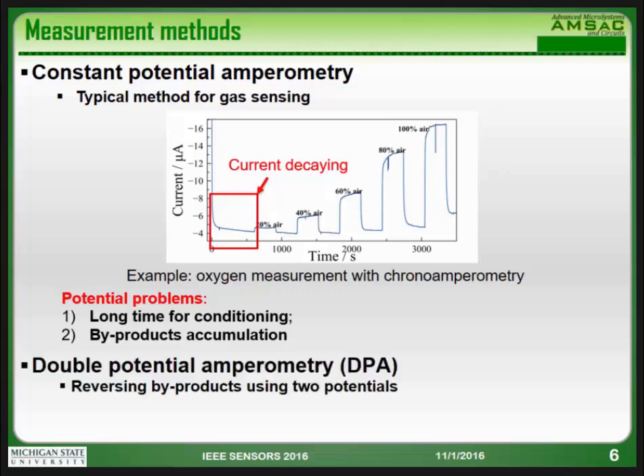So the advantage of the electrochemical method is that we can apply another potential, which means we apply two potentials on the working electrode, and we can reverse the byproducts. So we can overcome this byproduct accumulation. But the general double potential method also needs a relatively long time, because we also need to wait for a long decay time.